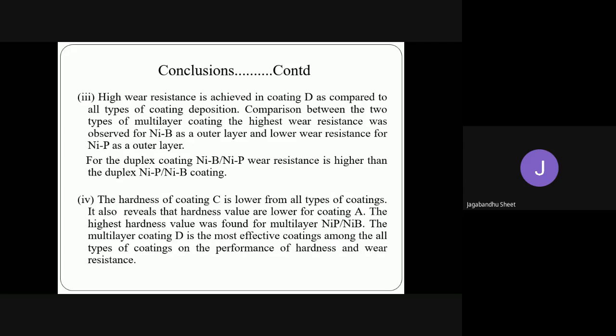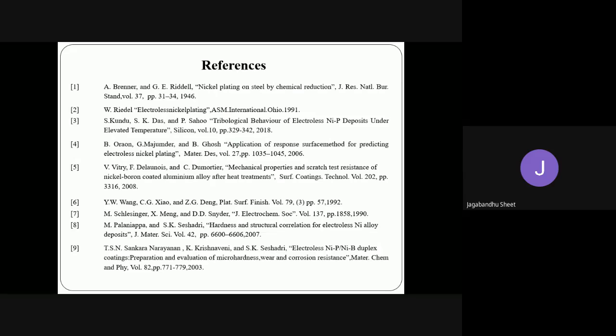The hardness of coating C is lower than all types of coatings. This is the multi-layer coating whose outer surface is nickel phosphorus, and its hardness is very low compared to all types of coating. It also reveals that hardness values are lower for coating A, and the highest hardness value was found for multilayer NiP/NiB. The multilayer coating D is the most effective coating among all types of coating on the performance of hardness and wear resistance. And these are the references used to prepare these experiments.